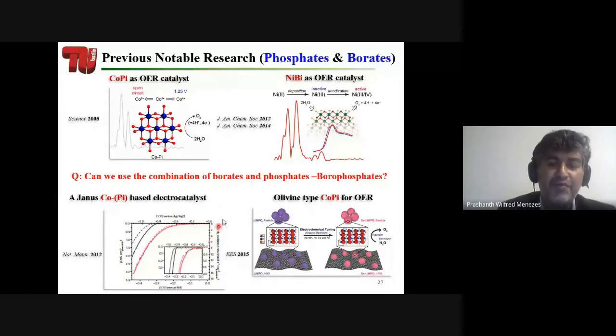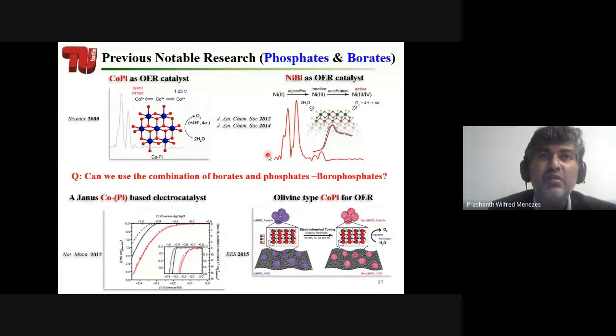So from this slide, what we can show is that phosphates or borates could be an important class of materials, because most of the catalysts used in the literature are oxide materials. We wanted to go away from oxide materials because they are well studied and there is no improvement in the activity that we could see now. So we want to find out what happens if you use structures with anionic parts, anions, or some doping, and so on. This is one of the important aspects we should look at, not only presently but also for the future.